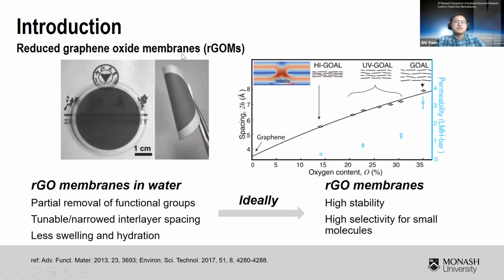There are several strategies to overcome this problem, and the most straightforward way is to remove the oxygen functional groups. It has been reported that the functional groups could be partially removed, and the interlayer space can be adjusted. And these RGO membranes have shown high stability and selectivity, which is promising for sieving small molecules or ions.